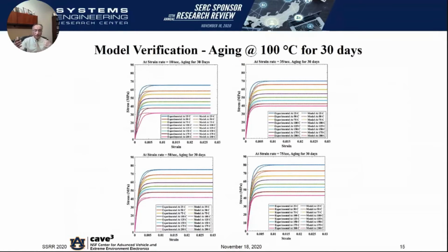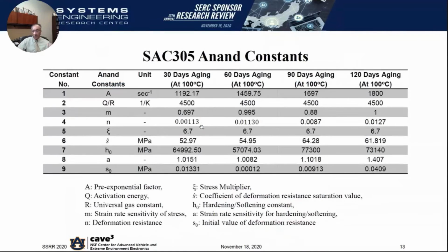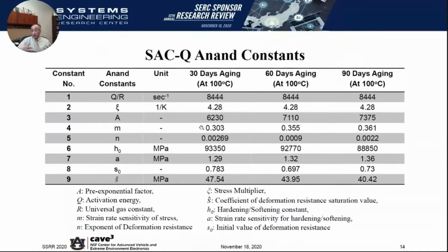So then the next question that one has to assess is, how well does this set of material constants actually represent the original data set that we started off with over a range of aging conditions, over a range of operating conditions, over a range of strain rates? So what we have then done is we have taken these constants that we developed and fit to the material model and said, okay, I'm going to just go ahead and simulate the high strain rate uniaxial tensile test and see how well the material actually replicates the behavior that I started off with.